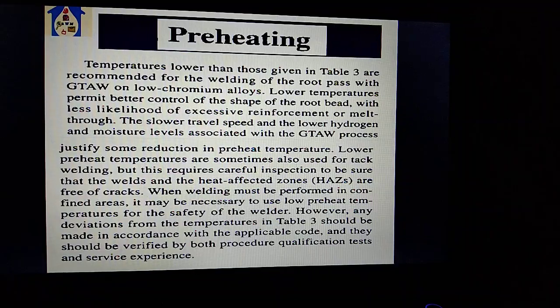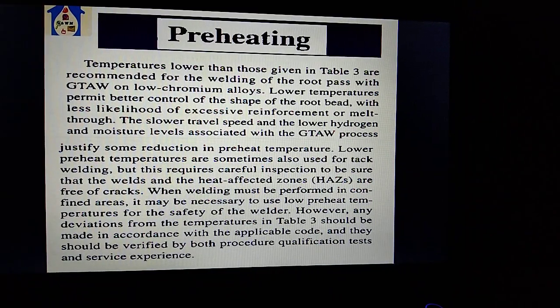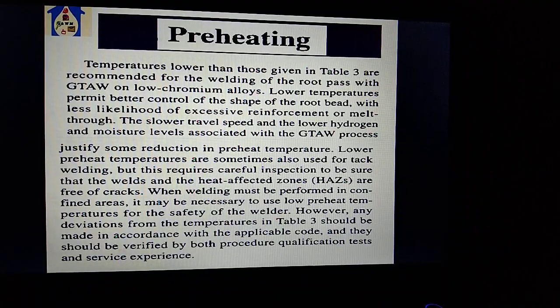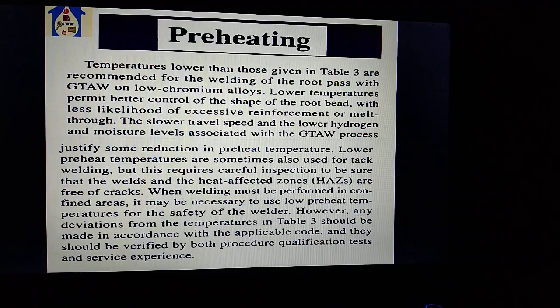Temperatures lower than those given in Table 3 are recommended for the welding of the root pass with GTAW on low chromium alloys. Lower temperatures permit better control of the shape of the root bead with less likelihood of excessive reinforcement or melting through. The slower travel speed and the lower hydrogen and moisture level associated with the GTAW process justify some reduction in preheating temperature.